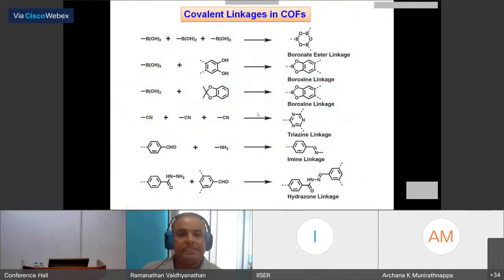Now, these are some examples of the kinds of covalent linkages based on which COFs have been developed. And these are very important linkages because they are reversible in nature. And this reversibility is very important to the uniform formation of highly crystalline COFs. And our interest is in aldehyde and amine-based COFs, which are imine-linked COFs. And this is because you can develop a wide range of aldehyde library as well as amine library, in a simple one-step or two-step reaction, which makes it very attractive for functionalizing as well as for developing highly crystalline COFs. And the imine linkages are very reversible, which is also very important for developing crystalline COFs.